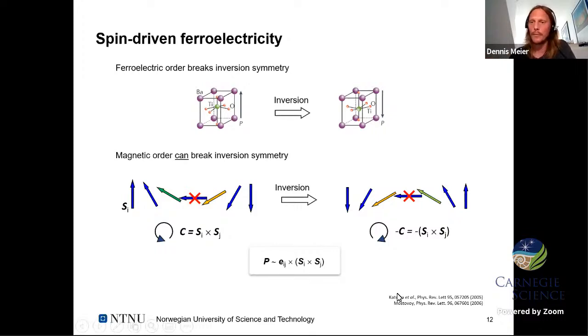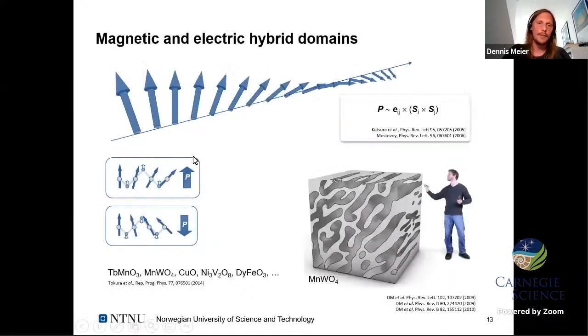Katsura came to the same results using a slightly different approach. What's important, and what I would now like to point out, is this one-to-one correlation between the polarization on the left and the spin system on the right. I illustrated that here a little better. So you see that we can have a rotation of the spins, which is clockwise. Polarization points up in this case. We can have a counterclockwise rotation of the spin system so that the polarization is pointing downwards. As I said, one-to-one correlation between polarization direction and spin system.